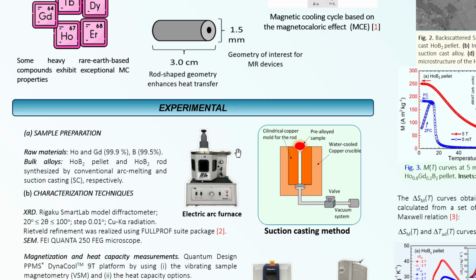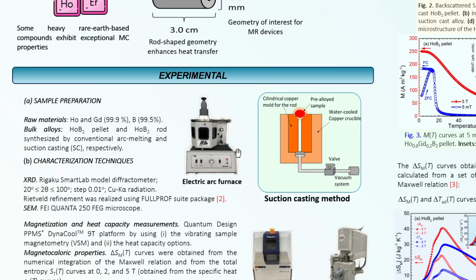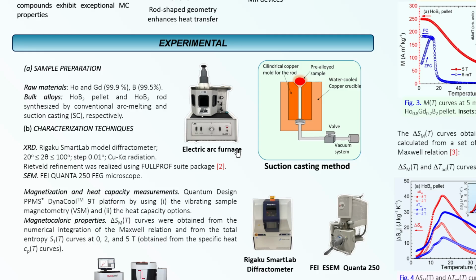To address this, we synthesize our alloys using 2 approaches. The pellet-shaped alloys were obtained by conventional arc melting, while the rod-shaped holmium diboride sample was produced using the suction casting technique. This technique is essentially a rapid solidification process. Once the pre-alloyed ingot is melted by arc melting, it is quickly drawn into a water-cooled copper mold by pressure difference, resulting in a cylindrical bar. This is important because it demonstrates the feasibility of fabricating device-ready geometries.